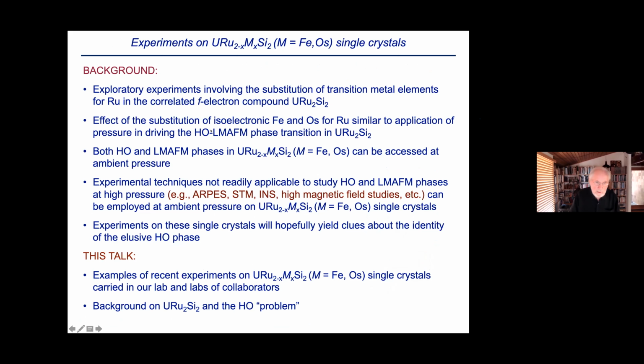And today I want to concentrate on the effect of isoelectronic substitutions of iron and osmium, because they're similar to the application of pressure in driving a transition from the hidden order phase to a large moment antiferromagnetic phase. And both hidden order and this large moment antiferromagnetic phase then can be accessed at ambient pressure through these substitutions of iron and osmium. So one advantage of this, apart from the fact that you do introduce chemical disorder or atomic disorder, is that experimental techniques that are not readily applicable to study hidden order and large moment antiferromagnetism at high pressure, such as ARPES, STM, inelastic neutron scattering, high magnetic field studies, and so on, can be employed at ambient pressure through these substitutions in single crystal materials.